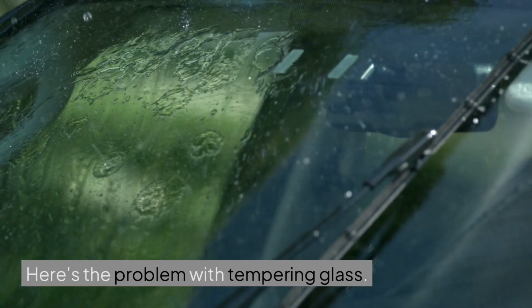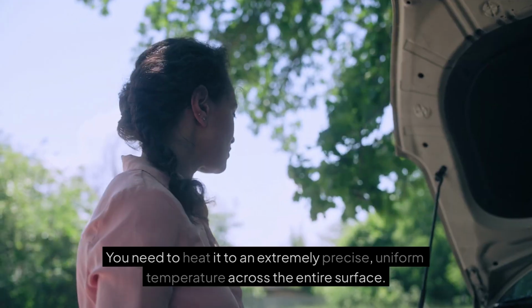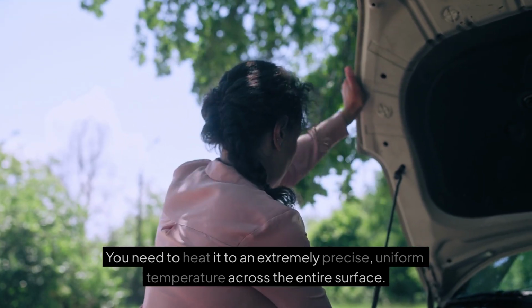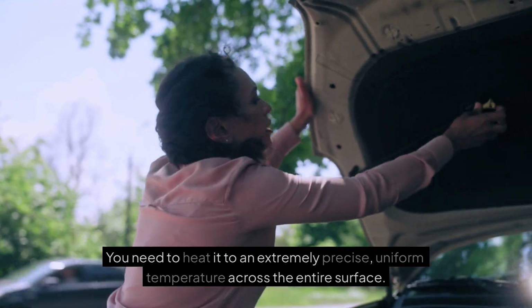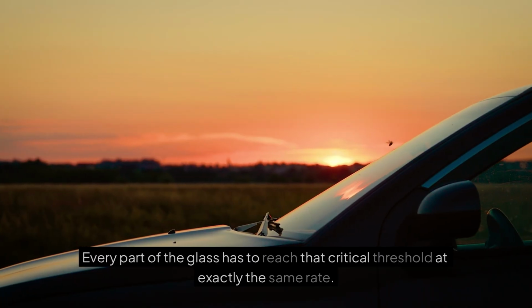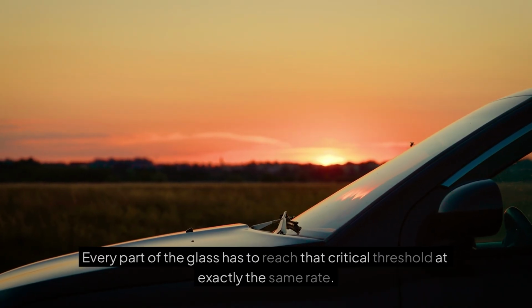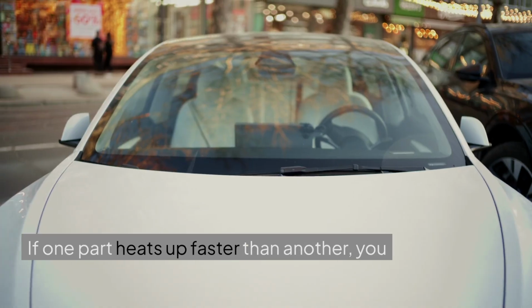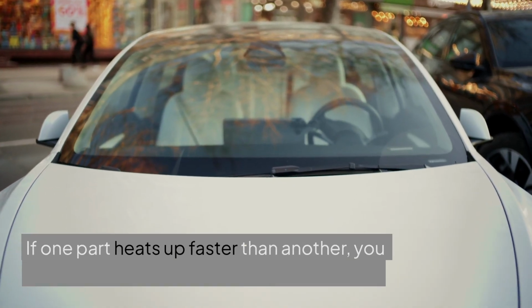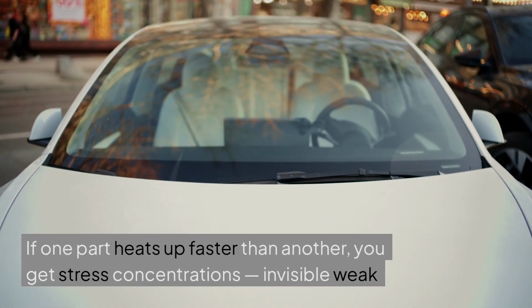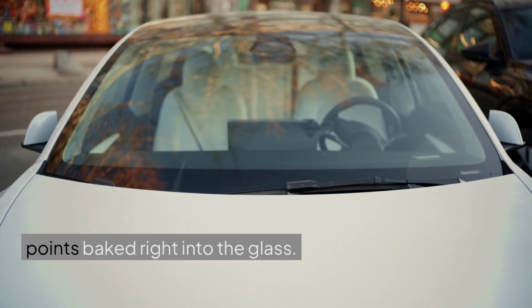Here's the problem with tempering glass. You need to heat it to an extremely precise, uniform temperature across the entire surface. Every part of the glass has to reach that critical threshold at exactly the same rate. If one part heats up faster than another, you get stress concentrations, invisible weak points baked right into the glass. And a window full of hidden weak points is a window waiting to fail.